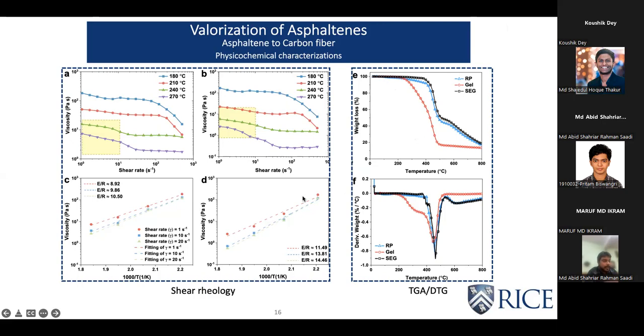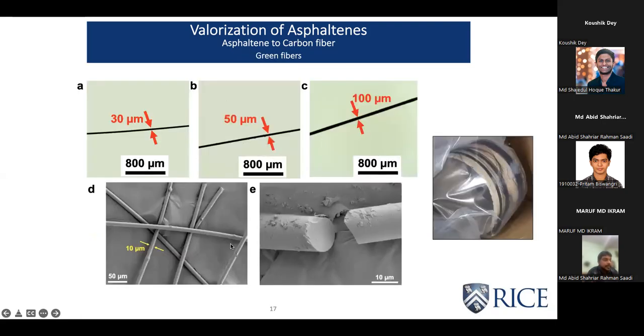So in summary, I'm not going too deep into the numbers because this would take a lot of time, and I want to share the results. But the core idea is that we took this asphaltene, did several types of physical-chemical characterizations, and determined the spinning parameters, which helped us extrude these green fibers in this form. We were able to extrude fibers with diameters ranging from 10 microns to 100 microns. And even towards the end, we were able to spin fibers in the form of these spools in large, bulk quantities.